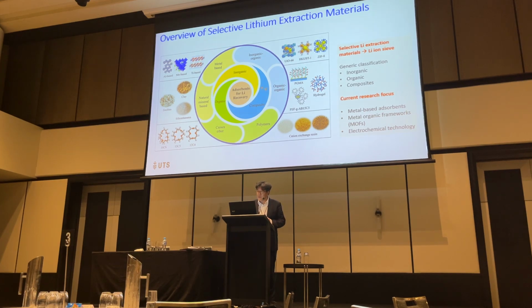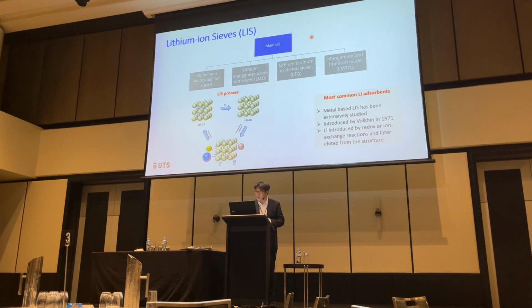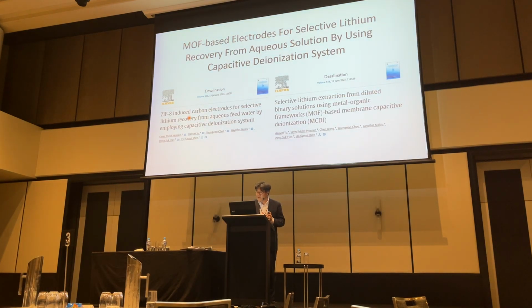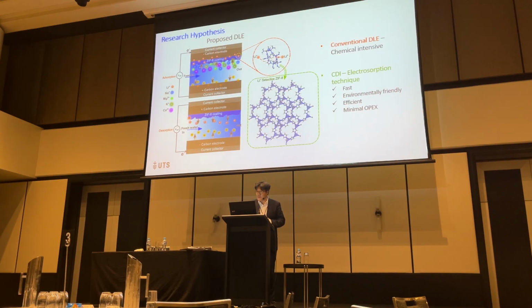There are many technologies you can use. Also, we have UiO-66 and ZIF-8, which look like very promising materials to selectively collect lithium. This is the basic theory of LMO, LTO, and LMTO: lithium is replaced with hydrogen so that it can easily be absorbed and dissolved. So it is an ion exchange mechanism utilized for selective lithium recovery. First, our experimental result is a MOF-based electrode for selective lithium recovery from aqueous solution using MCDI.